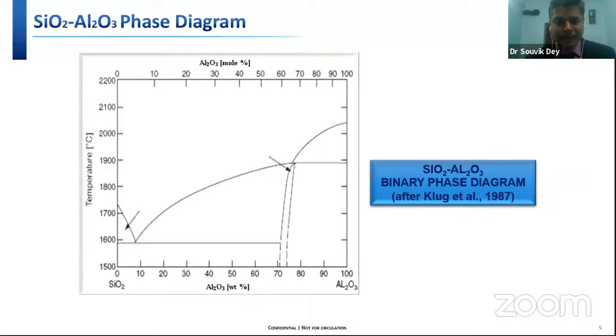Basically, the primary mullite, that is M1 mullite, with some kind of cuboidal shape, basically a rod-like morphology, was derived by decomposition of the spinel type structure of metakaolin, and the residual amorphous silica reacted with alumina, producing secondary mullite. Secondary mullite forms from a major solution precipitation process via a transitory liquid process, and the third kind of mullite, that is M3 mullite, is formed due to the presence of dopants facilitating nutrients for the growth of these mullite seeds, based on their crystallization habit.